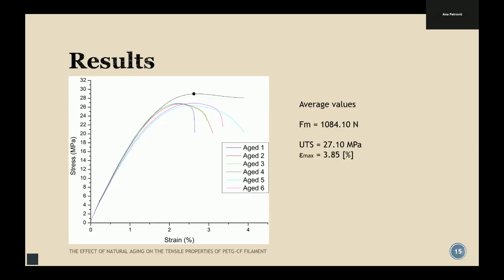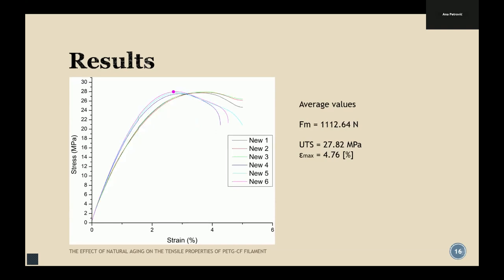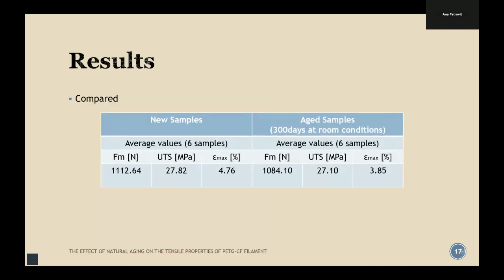What we can see here is the common behavior of PETG, nothing new. But if we look at the diagram for the new samples, we also see that the maximum force is around 1,000 newtons, ultimate tensile strength about 28 megapascals, and maximum deformation about 4.76%. We can also see that the two groups of specimens are diverse, so to say. When we compare these results in one table, we can see that for maximum force there is not a big difference. Also for ultimate tensile strength. The only difference is for the deformations.